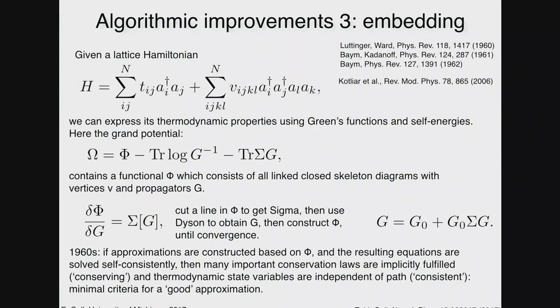Once you know phi, then the derivative of phi with respect to g gives you the self-energy. The self-energy gives you the Green's function. Out of the Green's function, you can reconstruct the Luttinger-Ward functional self-consistently, and that gives you a smart way of approximating diagrammatics, because as Baym and Kadanoff told you back in 1962 or so, if you make approximations to that Luttinger-Ward functional rather than, say, to the Green's function or the self-energy, you can guarantee a couple of important conservation laws that, for example, make sure that you're not losing particles as you time evolve your system.